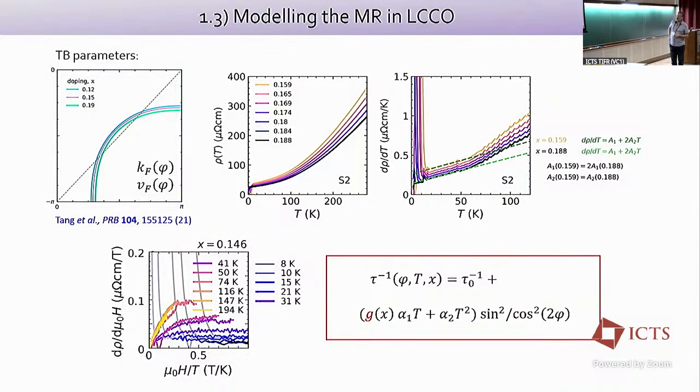And then the final thing is, because of this propensity for the low temperature, high field magnetoresistance to be linear, this indicates to us from analysis we've done on other systems that there have to be some very strong scattering centers, so-called hotspots, in the system.